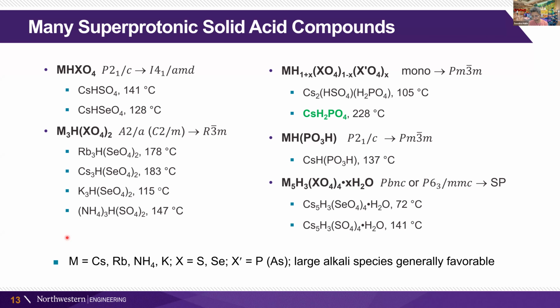And then there's some other sort of messy ones that are hexagonal in structure, and the high conductivity structure is not known for those materials. A general feature is that these materials all have some alkali species, large alkali, typically cesium or rubidium, sometimes as small as the ammonium ion or the potassium ion. The polyanion group is typically sulfate or selenate, can also be phosphate or arsenate.